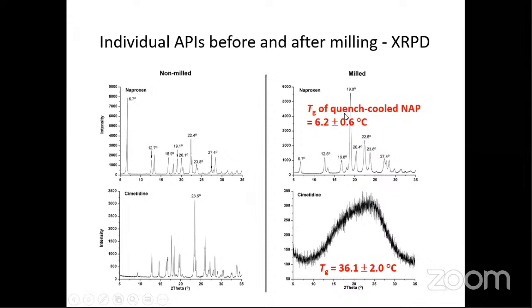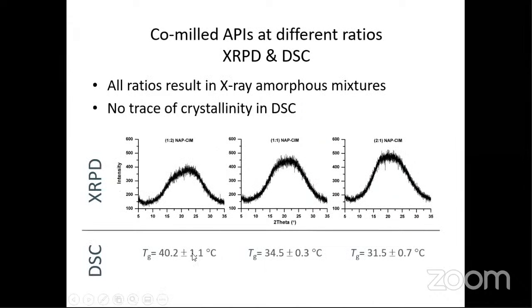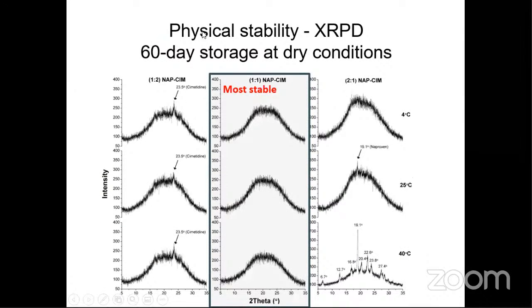In this case we used quench cooling. We used mixtures with 1:2, 1:1, and 2:1 molar ratios - different molar ratios - and all three samples we prepared became amorphous. The Tg results show the highest Tg was observed at the 1:2 molar ratio, around 40 degrees.